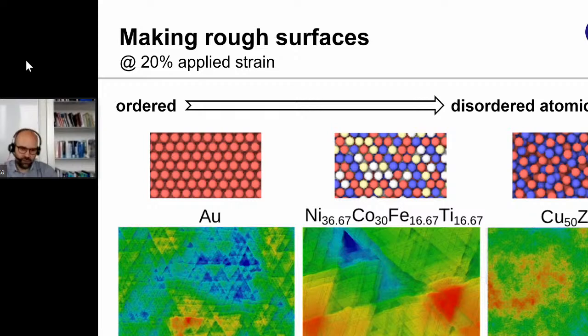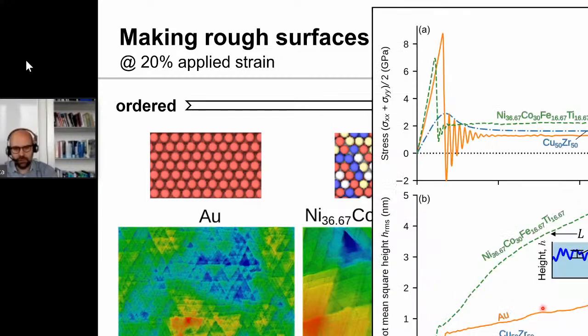On the crystalline system, you nicely see these little triangular structures that represent the lattice planes of the crystal. What you see here is a 111 surface, and these are actually the slip planes of dislocations that exit the surface. I'll come back to that in a second. This is the high entropy alloy that looks similar, and the glass is smooth.